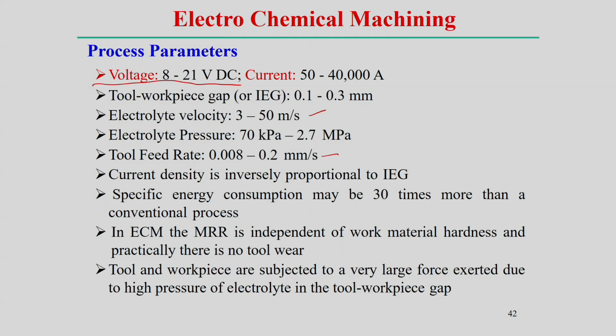If you see the feed rate is very small, it can be 0.008 to 0.2 millimeter per second only, and current density in these cases normally depends inversely on the gap between the workpiece and the electrode, but in this case specific energy consumption becomes very high, almost 30 times more than that of the conventional process.